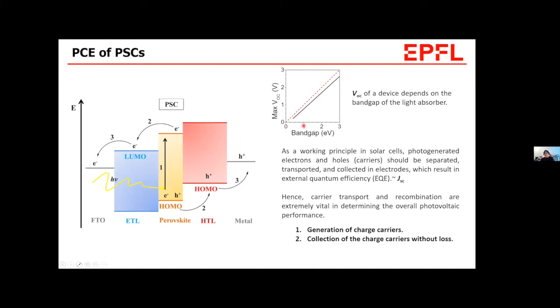But the VOC is, as I said, limited by some factors, for example, charge recombination in the bulk and at the interface. So reduction of non-radiative recombination is important to have high VOC. And for JSC, short circuit current, the photogenerated charge carriers should be well contained and well collected to the electrodes to result in current. In other words, collection of charge carriers without loss by recombination is important to obtain high current. So here again, limiting the non-radiative recombination is important.